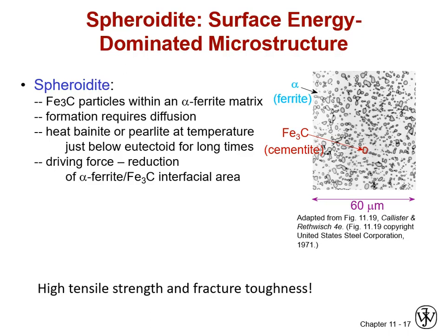And one way that we can use that to our advantage is to allow cementite to precipitate from a different starting constituent and then literally cook it. Leave it in the furnace at a reasonably high temperature, close to eutectoid, maybe above 650 or so, and let the drive for reduction in surface area go from maybe a platy structure or an angular cementite precipitate particle to a sphere. Excuse me. If you have a fine network of these spherical cementite particles, you can still get excellent strengthening.